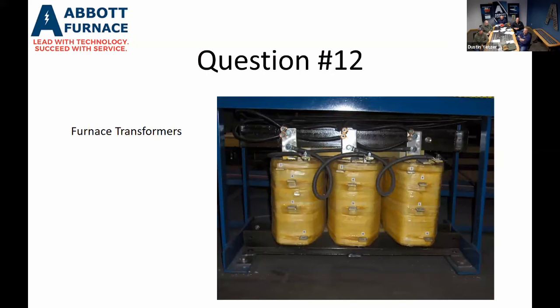Then if you determine that your glow bar's resistance, as the glow bars wear, the resistance goes up. So if that resistance has increased enough that you're not pulling enough power to heat that zone up, then you're going to have to move up a tap, which is a voltage tap. As in the picture here on this transformer, you see the numbers on those different taps. That's a voltage tap, and the higher the number that you go, the higher the voltage is on that particular tap. So usually you start off on tap 1 or tap 2, and then as the glow bars wear, you move up to each tap as they go.